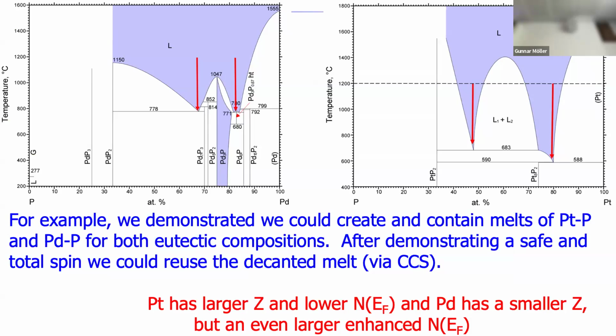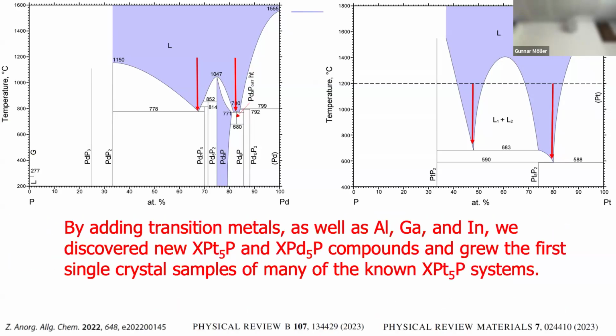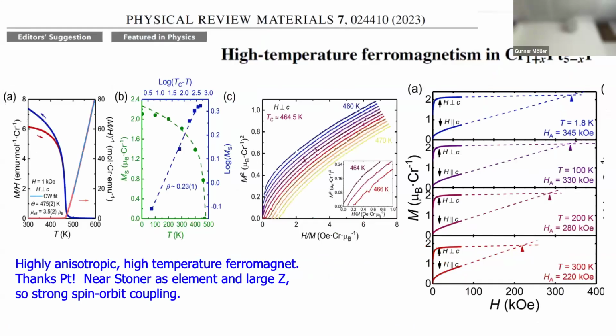All right, so platinum has a large Z, but a lower density of states. Palladium has a smaller Z, but a larger density of states in elemental form. Okay, but it's something to keep in mind. So by adding various transition metals as well as aluminum, gallium, indium, we've discovered new X-platinum-5-phosphorus, X-palladium-5-phosphorus, and also grown the first single crystals of some of the known ones. Let me show you what you can do with it.